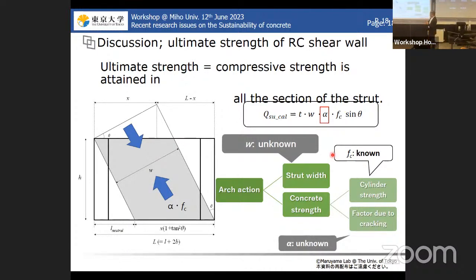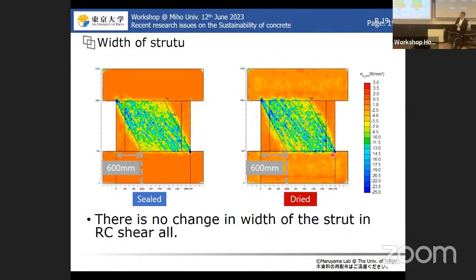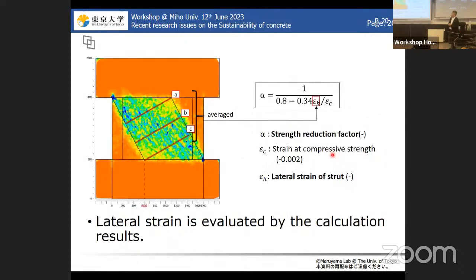So basically, the ultimate strength can be calculated based on arch action, and we also have to think about strut width and the concrete strength in the concrete shear wall. And this concrete strength is based on the material property, but also the factors which affect the compressive strength here due to the cracking. I will explain a little bit. So to calculate the strut width, we confirm that the width of the strut before and after drying is completely the same. And if we think about the concrete strength here, we can calculate how much strain is observed in this direction, which has an influence on the concrete strength in this shear wall.